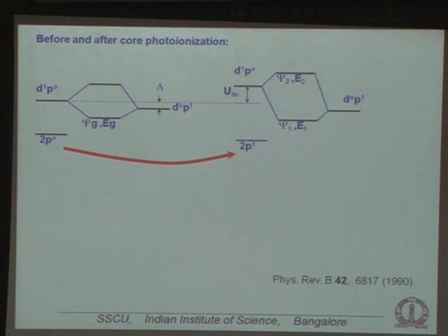But you see, this probability as well as this energy difference will depend on delta plus U_DC, and the energy difference will also depend on T. So in detail, by simulating the spectrum, getting the intensity and the energy separation right, I'll get an estimate of delta, U_DC, and T. In fact, this is a Mickey Mouse problem because essentially it's a one-electron problem, because I have only one hole here. And this second hole that I put in doesn't have a dynamics, meaning it cannot jump to there because it's a deep core hole, so it provides only a DC shift. So this can be solved in closed form.